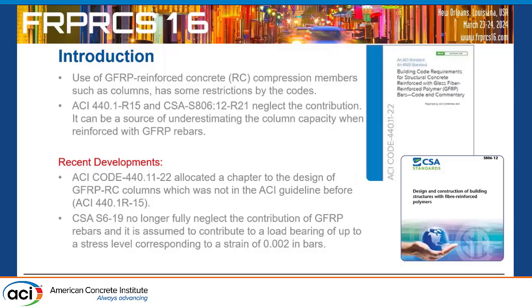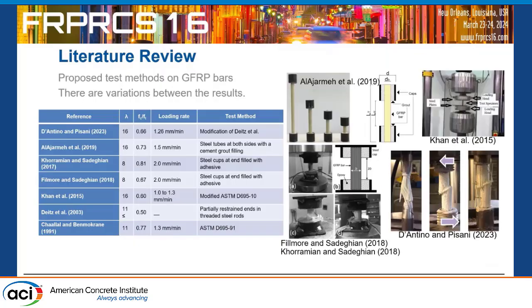Just to give you a background, I'm from Canada. The Canadian code, which started probably 4 or 5 years ago, allows up to a strain of 0.002. So the contribution of FRPs in compression up to that level is considered by the bridge code. And there is another code, S806, which is the building code in Canada, and they are considering 0.002 as well. But even 0.002, I think, is conservative. But at least in ACI, we can match the Canadian version. So that's the story and the problem that we are going to solve.